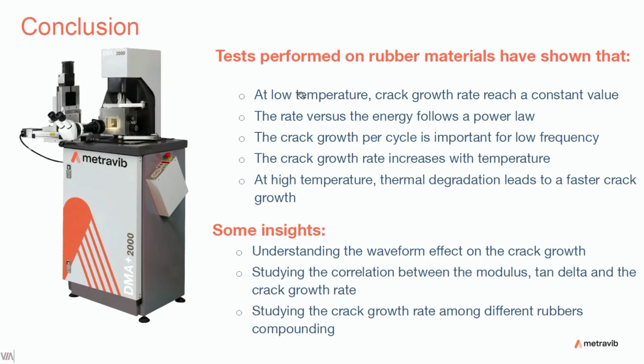As a conclusion, tests were performed on rubber materials, and results have shown that at low temperature, crack growth rate reaches a constant value. The rate versus the energy follows a power law. The crack growth per cycle is important for low frequency, and the crack growth rate increases with temperature, and of course at high temperature, thermal degradation leads to a faster crack growth.